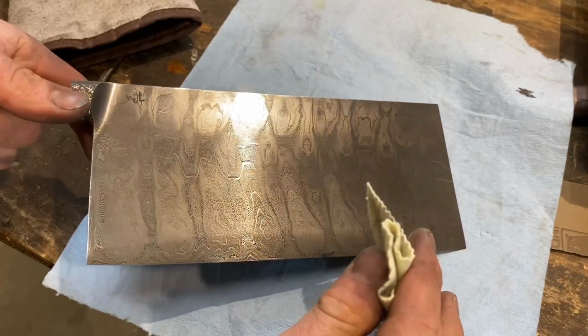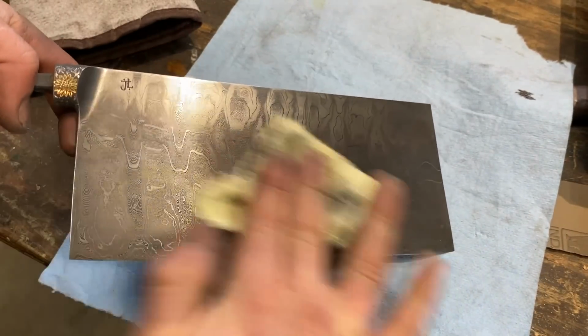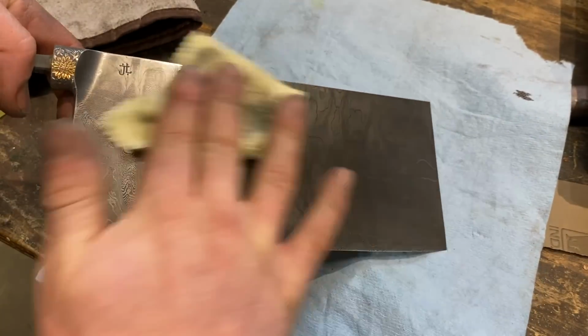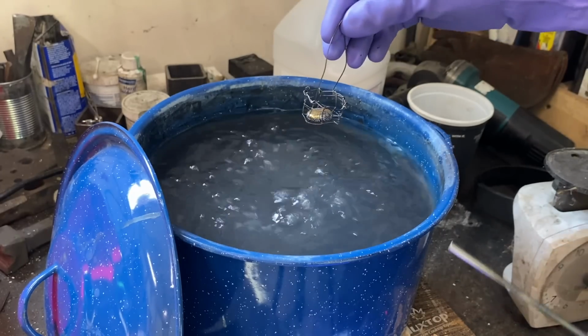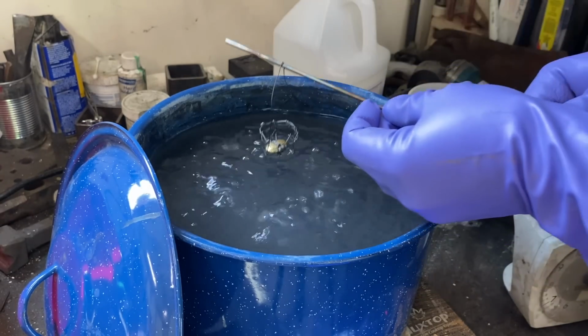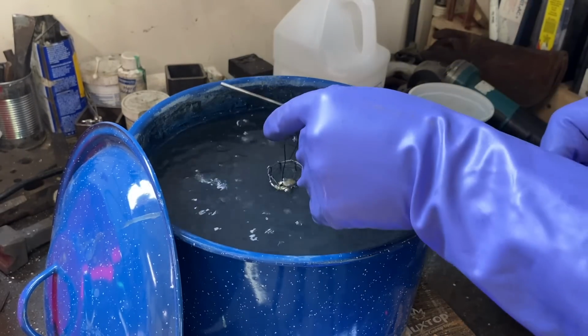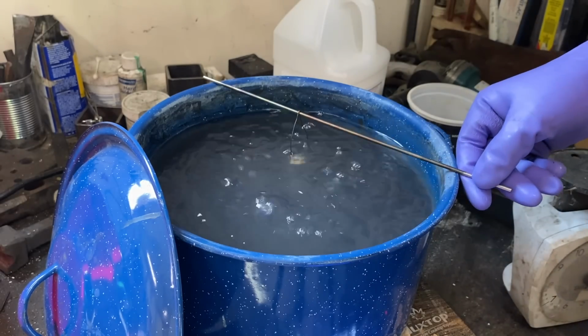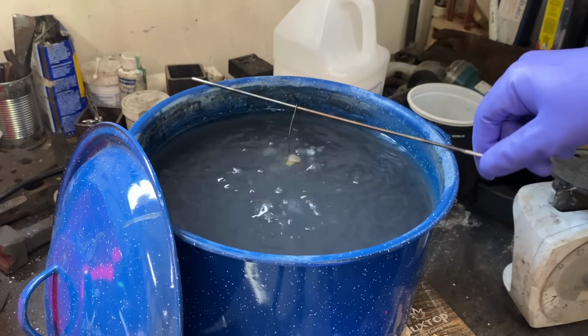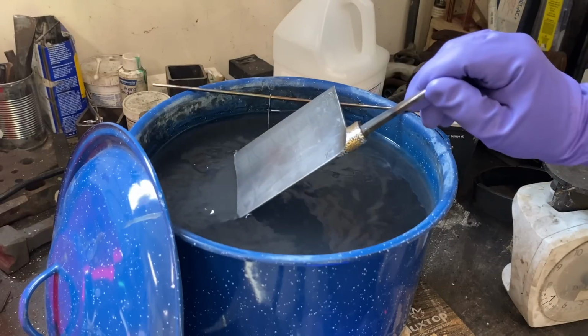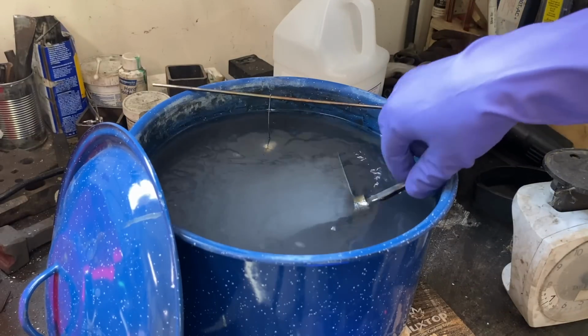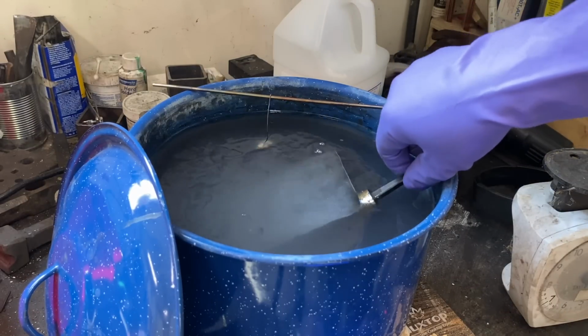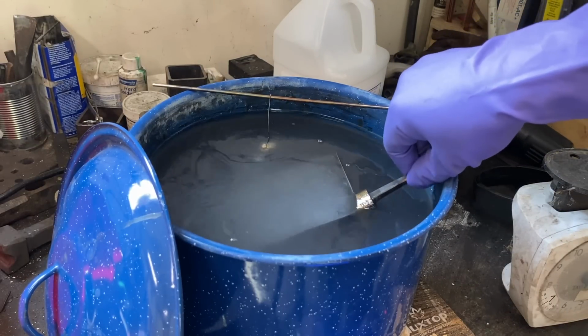At this point I'm very happy with the shimmery pattern, but I still need to darken the background of the Koftgari to contrast with the silver and gold and make them stand out. Hot caustic bluing of the kind that's used on firearms is my favorite way to achieve that high contrast look. The boiling salt solution leaves a durable and attractive black oxide finish on the steel, but it doesn't affect the silver and gold in the slightest.